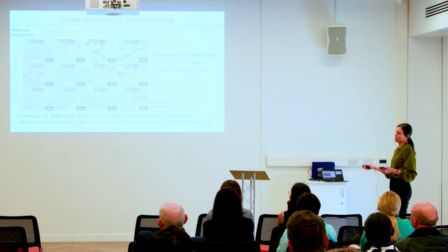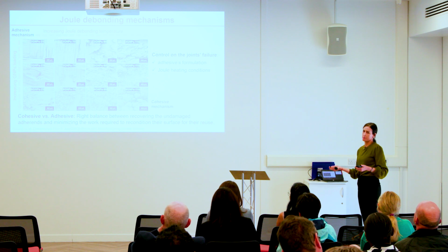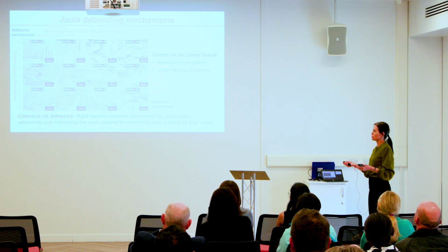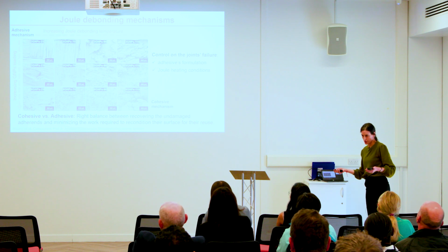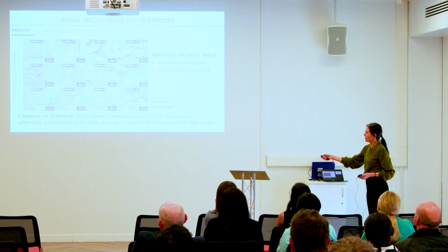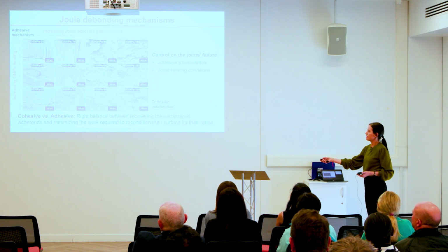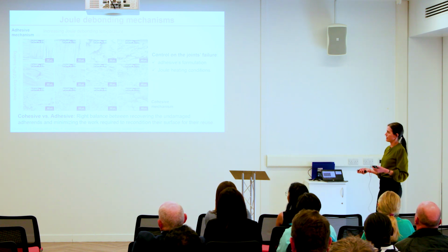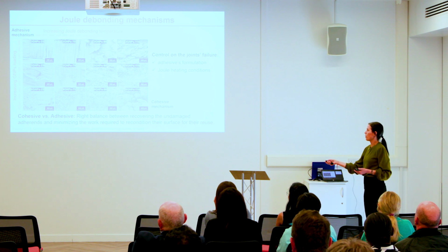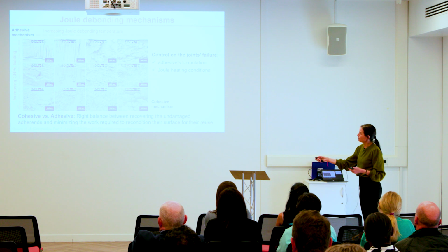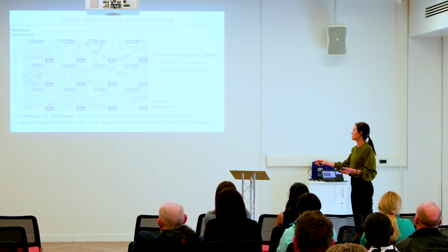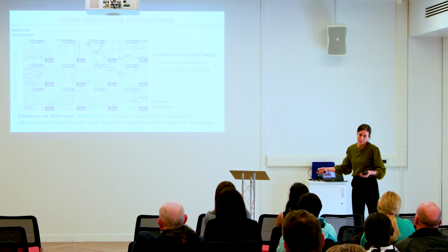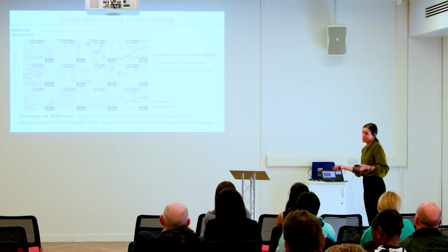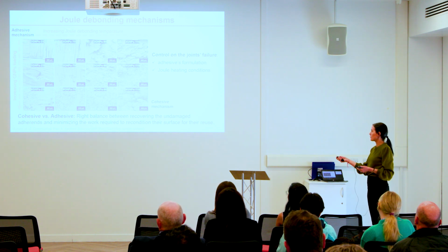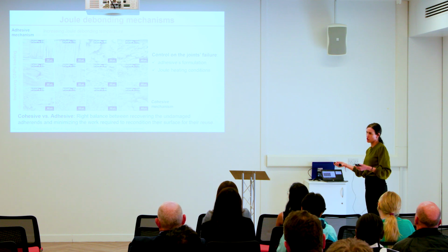Finally, what about the Joule debonding mechanism? Here we see some SEM pictures corresponding to the fracture surface after Joule debonding using different experimental conditions. And we see that as we increase the Joule debonding temperature and the amount of graphene incorporated into our adhesive, we are progressively promoting the cohesive failure mechanism, whereas lower Joule debonding temperatures and lower amounts of graphene incorporated into the adhesive tend to progressively promote the adhesive failure mechanism, which basically means that we can indeed control the joints failure just by controlling the adhesive formulation and the Joule heating conditions.